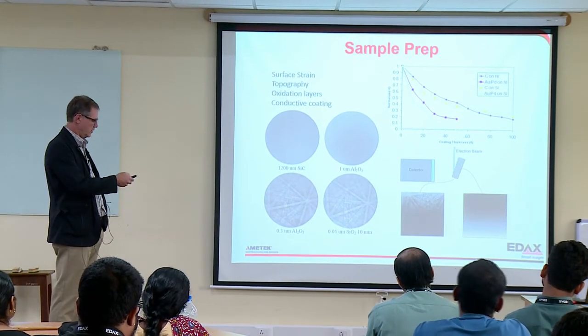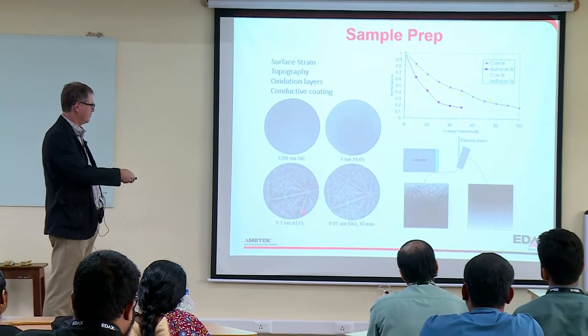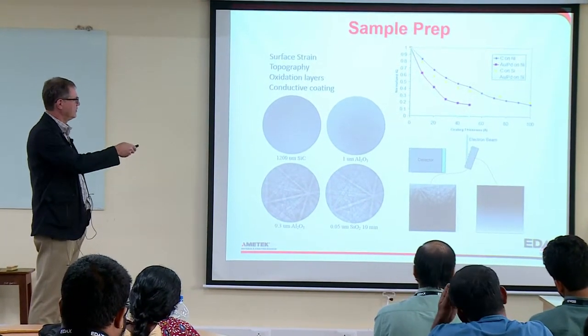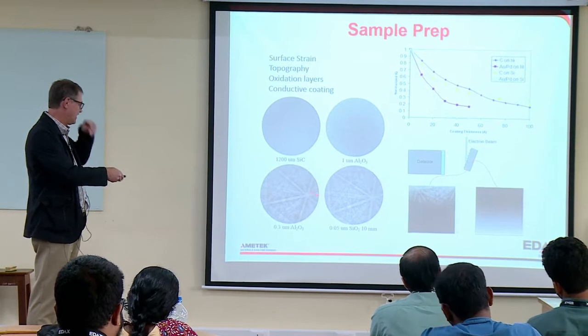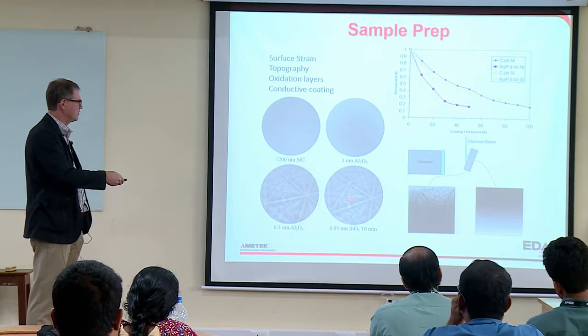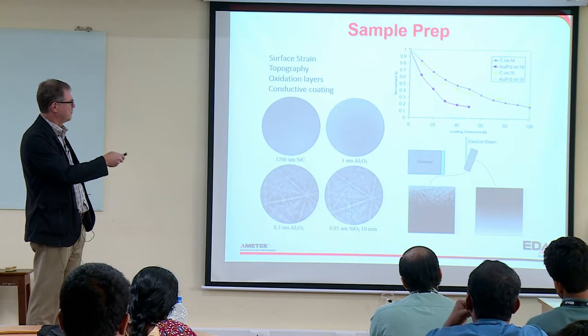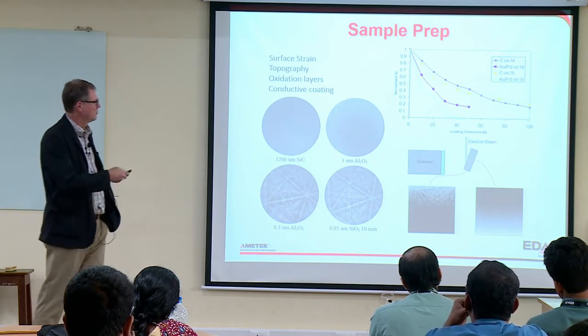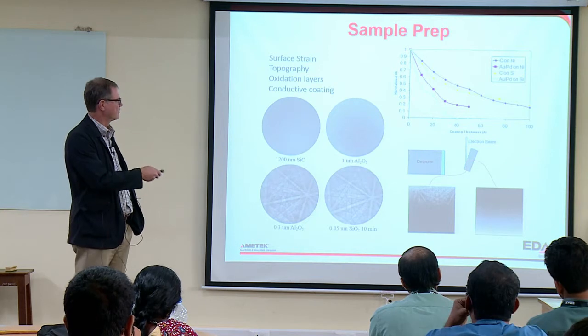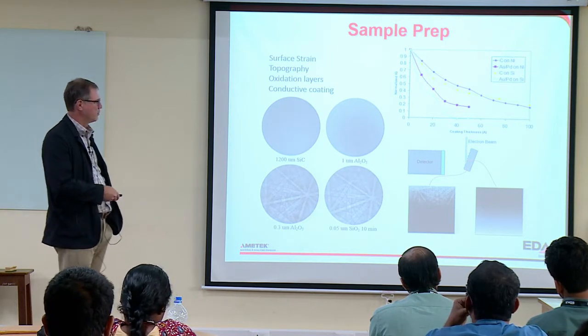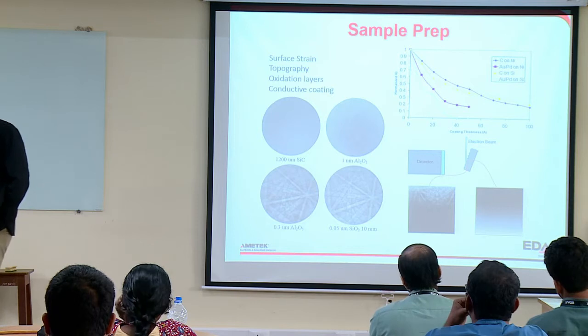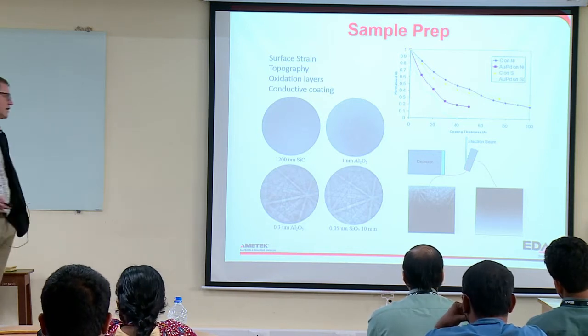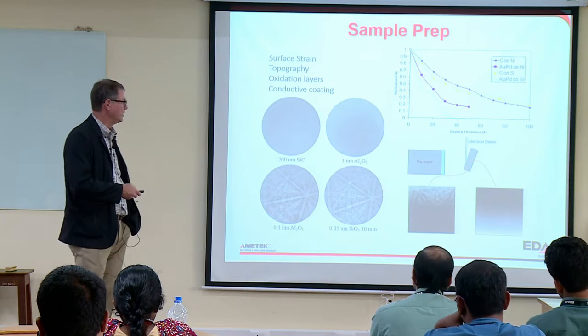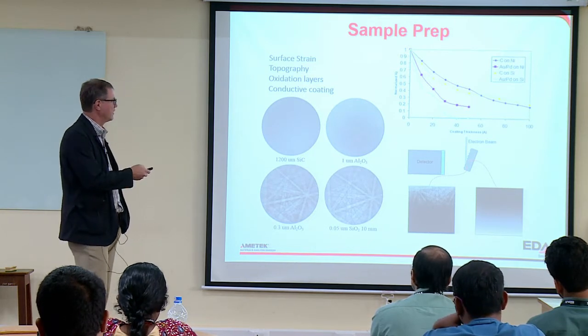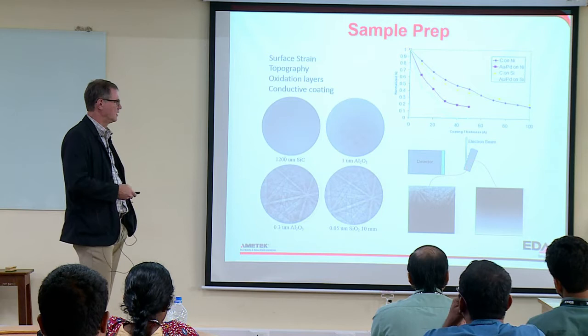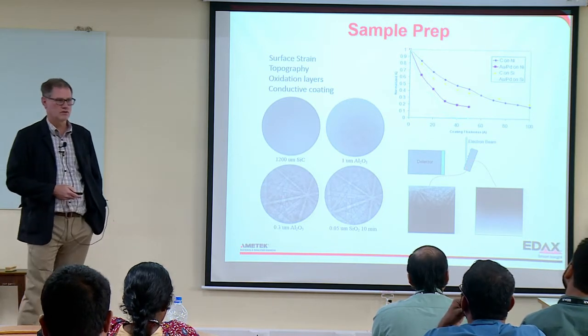And so if you look at the image quality, which is a description of how good these patterns are, you can see that this will have low image quality, this will have high image quality. The other thing that can affect that is if you have to coat your materials. If you do too thick of a coat, the image quality goes down very quickly. And so if you're working with non-conductive materials, ideally you would do it in an environmental SEM, but if you don't have access to that, then you probably need to coat them. And if you do that, we recommend using a very thin coating of carbon. That seems to give the best results.